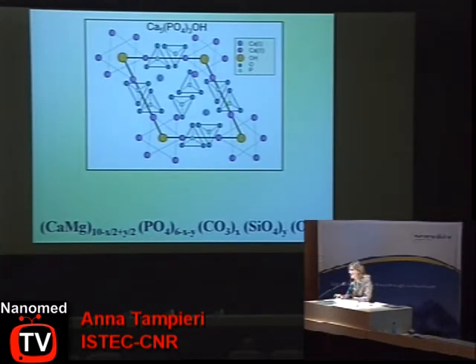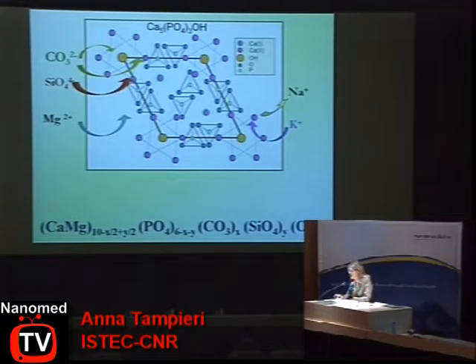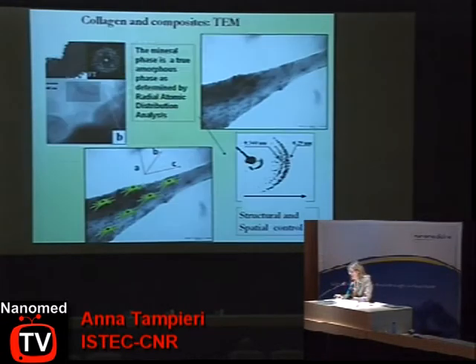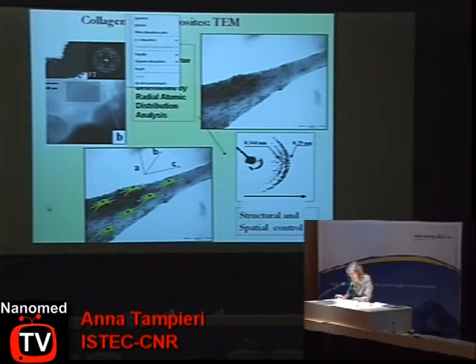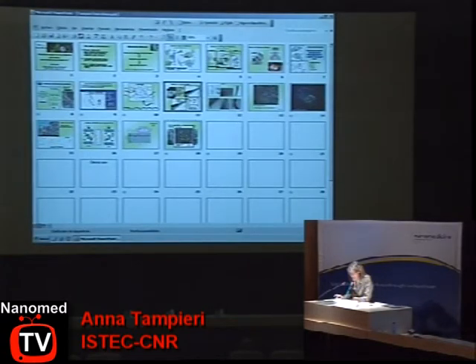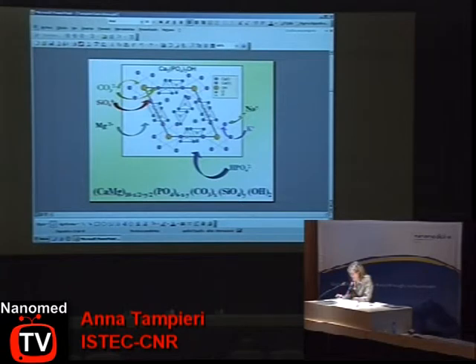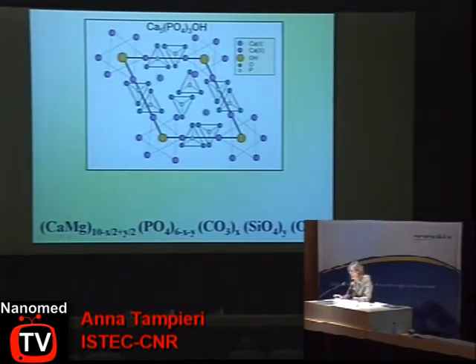It's well known that the human natural apatite is very far from the stoichiometric formula, and many ions present in the physiological environment enter in the structure of apatite. The final formula of a biomimetic apatite is what you can see at the bottom. And those ions can enter in the structure thanks to the low crystallinity and the high instability of this biomimetic hydroxyapatite.